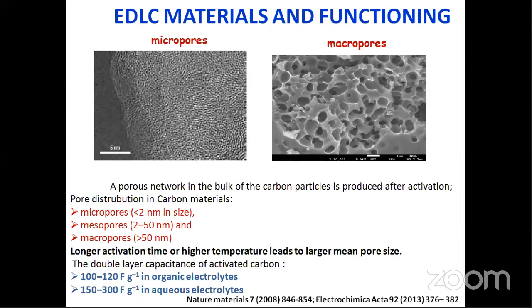For example, potassium hydroxide, sodium hydroxide, zinc chloride. You can see the difference when you use different activating agents. If you use zinc chloride, you can have controlled pores. At the same time, you have to optimize the activation time, such as 2 hours, 4 hours, 6 hours at a particular temperature, or you can fix the time and vary the temperature. If you play around with the pyrolysis and the external conditions, you can get a variety of properties of these carbon-based EDLC materials. Of course, as I mentioned, for such carbon materials with double layer formation, in organic electrolytes they have 100 to 120 farad per gram.